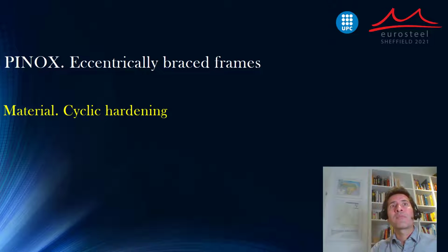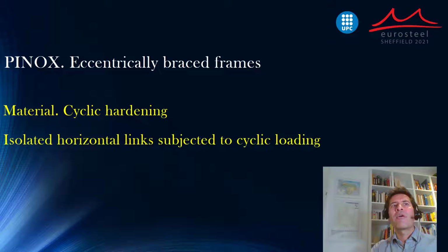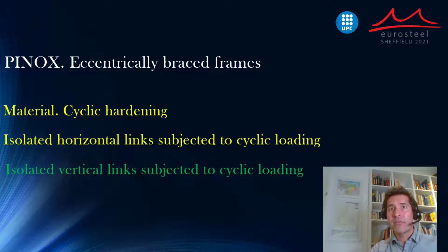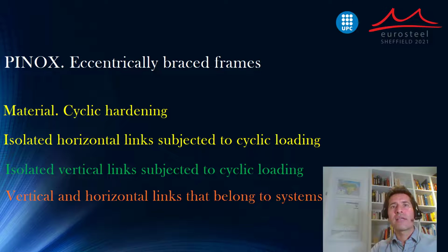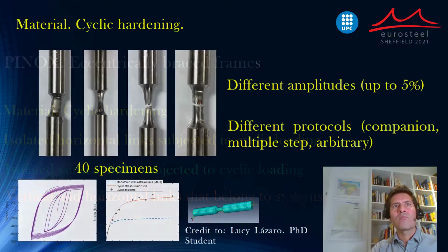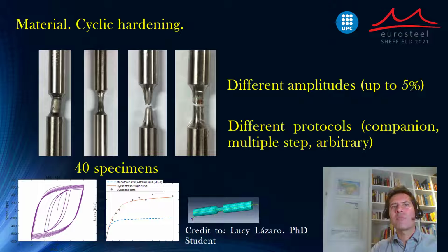In this research project, eccentrically braced frames have been studied from the materials perspective, cyclic hardening, from the perspective of isolated horizontal links, isolated vertical links, and vertical and horizontal links that belong to systems. From the materials perspective, a vast experimental program on 40 specimens was tested under different amplitudes of deformation strain up to 5%, under different protocols like companion, multiple step, or arbitrary, and that belongs to a vaster program of a PhD thesis that is currently being elaborated by Lucy Lázaro.